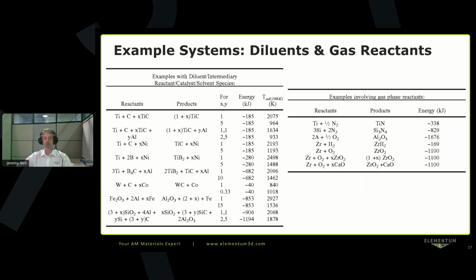Now, to control the reactions, this is where you can add in diluent phases. You can either add in pre-synthesized product phase, or you can add in metals. In our case, we're typically adding in metal alloys that you want to produce, in addition with these smaller amounts of reactively produced ceramic type products like carbides and borides. And so by controlling that balance, you can control the energy from the reaction versus the energy input needed from the laser. And you can control the composition, particle sizes that you're forming, phases that you're forming, and so on.